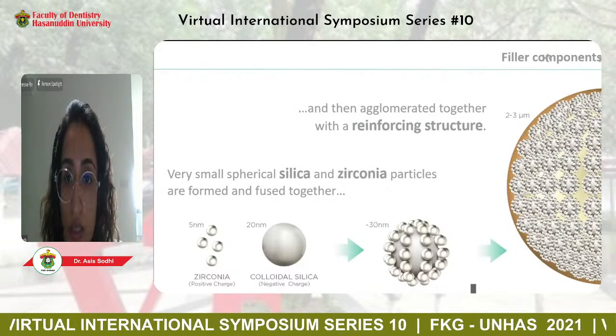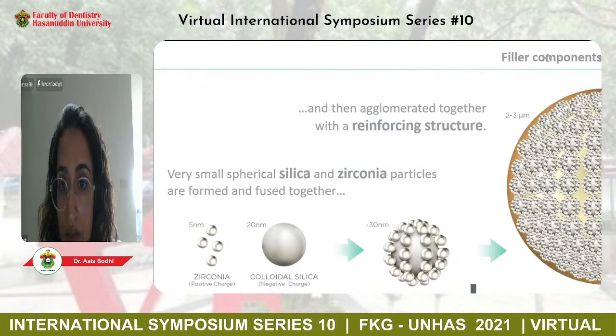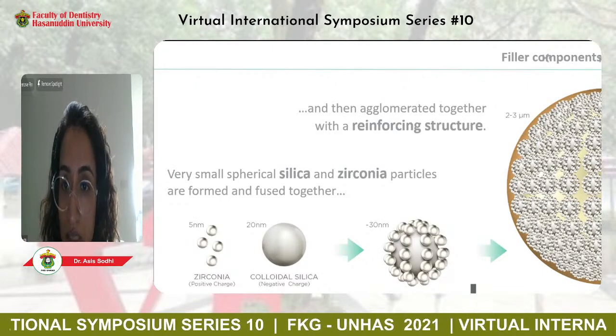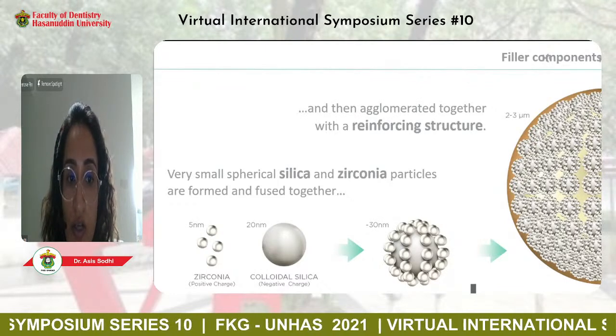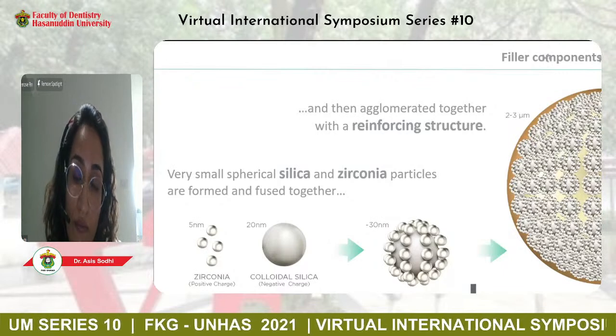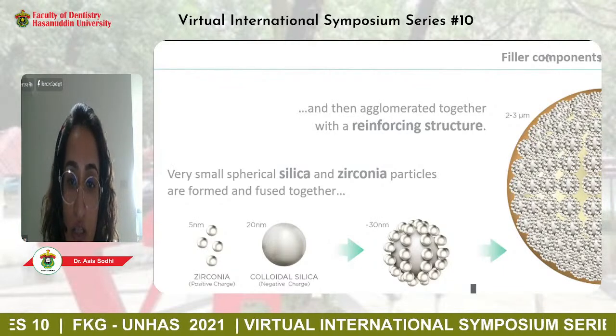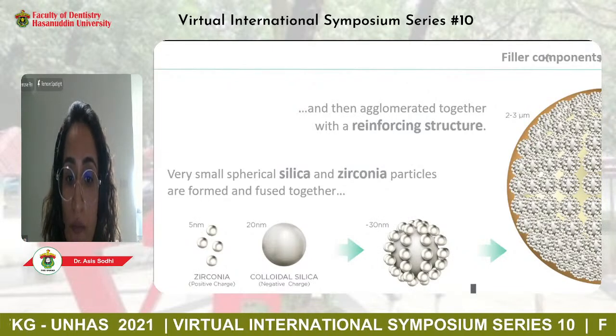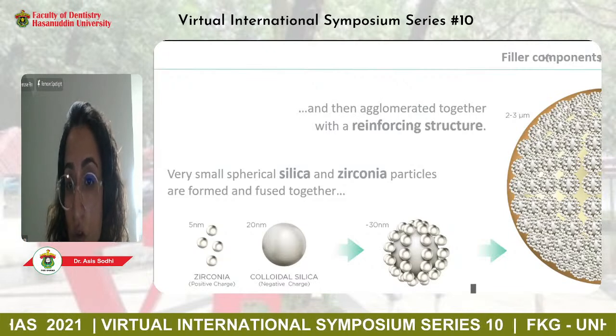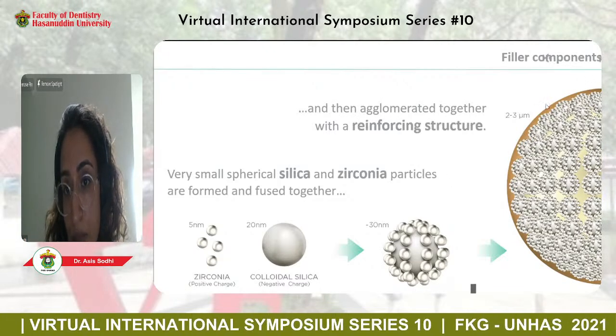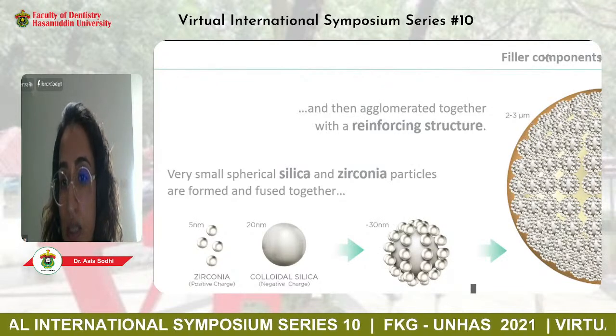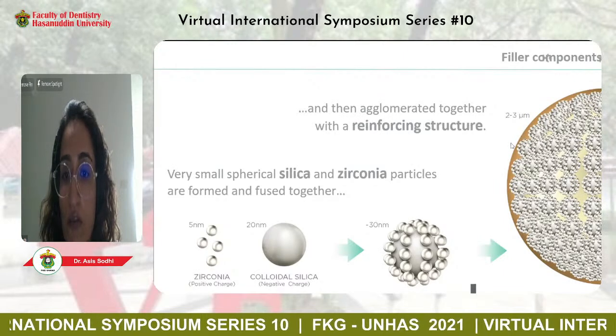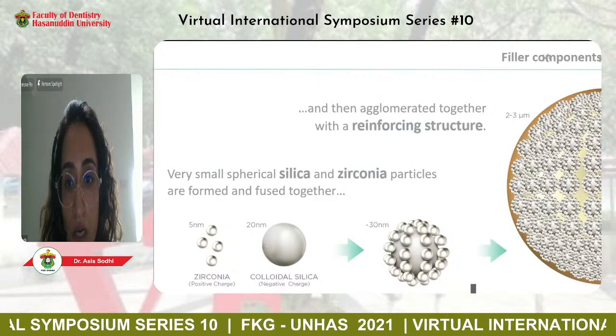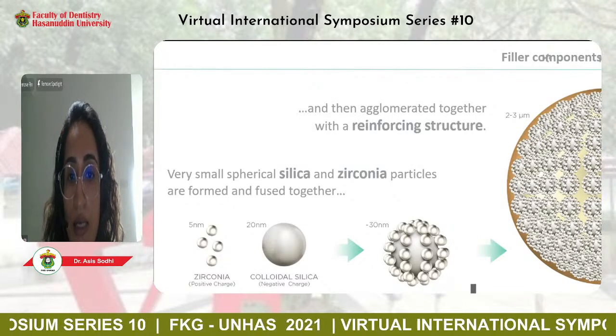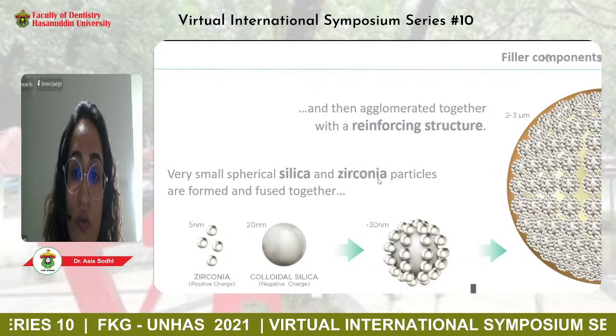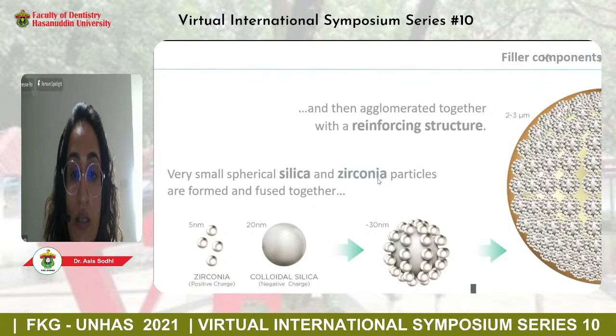Now, what is the science that we've used in this material? What is the filler technology, which is key for all the characteristics? We have used silica and zirconia particles. Silica by nature is negatively charged, and zirconia is positively charged. So both of these are oppositely charged particles, and they fuse together and form spherical balls. These spherical balls are then infused into the resin matrix. You can see this brown substance here is a pictorial representation of the resin matrix. So we infuse these into the resin matrix in order to form the composite material. The basic science is using silica and zirconia infused spherical filler particles in the resin matrix.